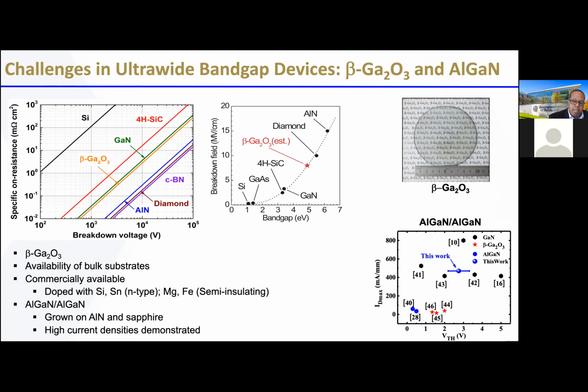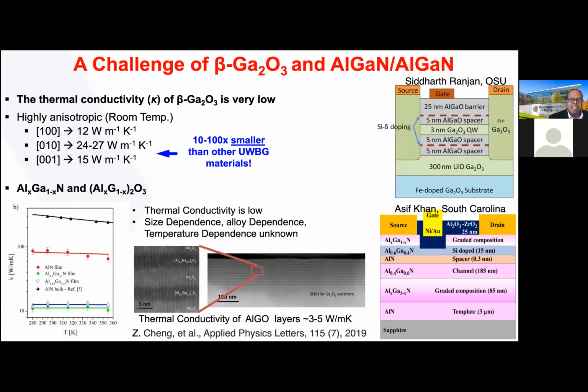These are very interesting things, but when you start looking at where we start running into problems, the thermal conductivity of beta gallium oxide is highly anisotropic. The highest thermal conductivity, in the [010] direction, is on the order of about 24 to 27 watts per meter K. This is 10 to 100 times smaller than other wide bandgap materials. When we move to ternaries like aluminum gallium nitride or aluminum gallium oxide, we're only finding very few reports in the literature that even talk about the thermal conductivity of these materials.